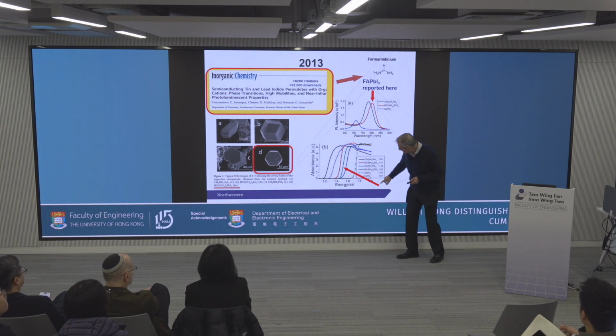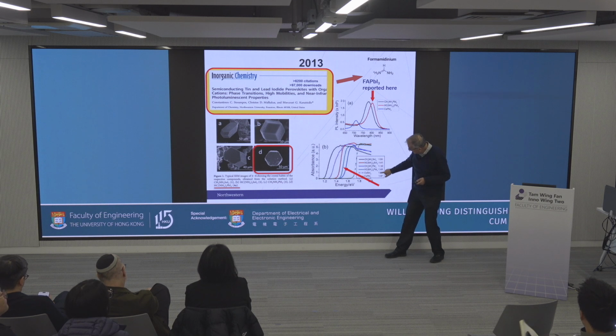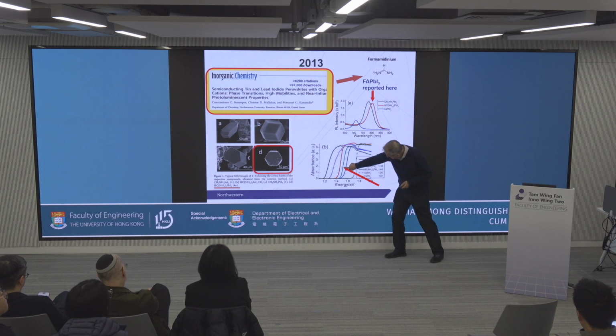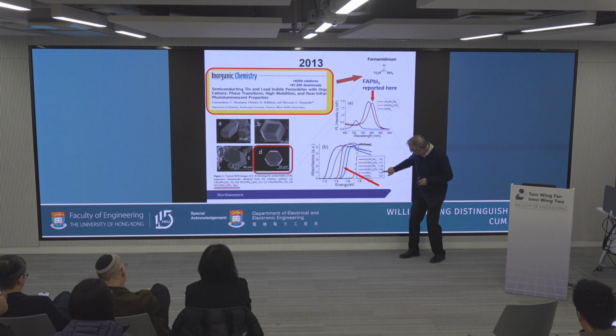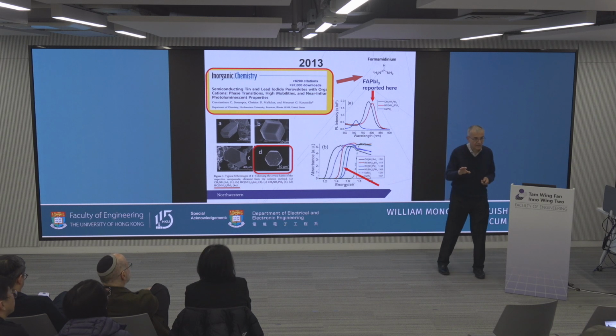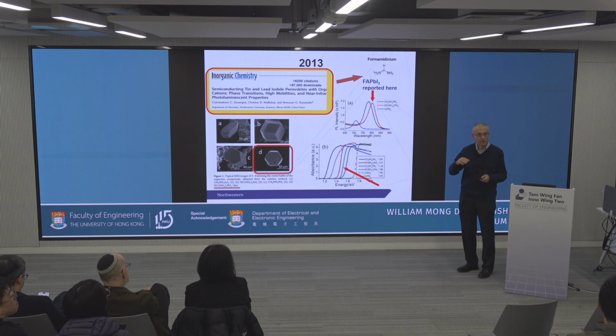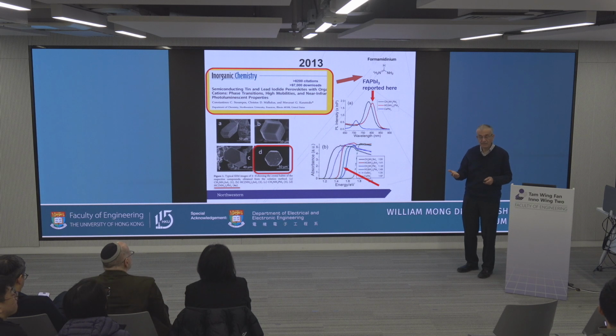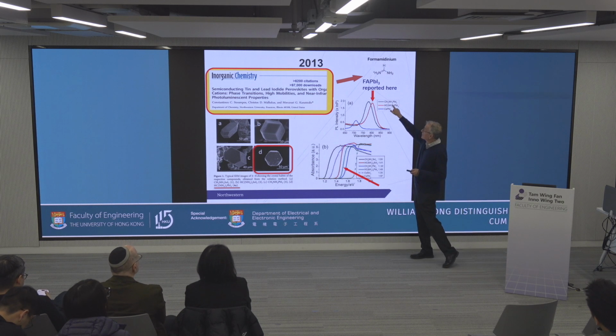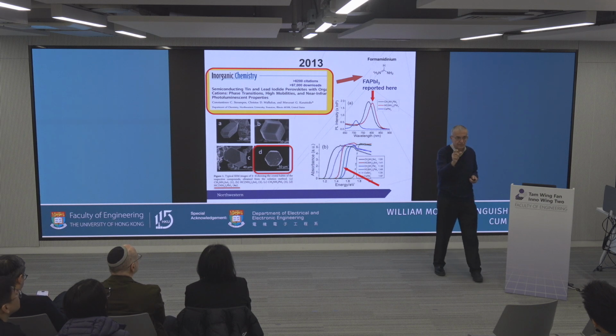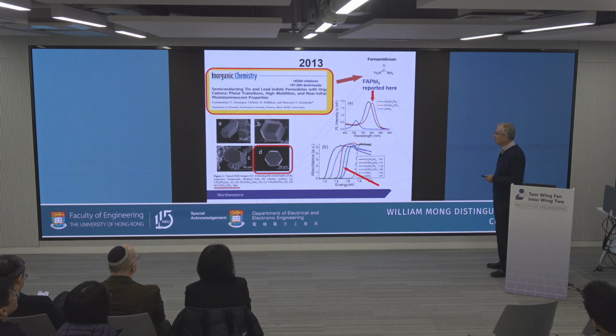And here's the absorption, and here, of course, is lead and tin. But again, this is the spectrum of the formamidinium, which is 1.48, whereas MAPI is 1.55. And people notice this, say, "Wow, what is this? This absorbs a little bit more light. Maybe we should use this." And now all the top perovskite solar cells that break efficiencies, reaching 26, 26.5, 27, they're based on this material with a little bit of doping with other cations.